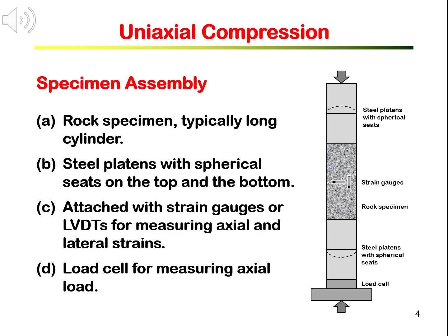We will need to measure deformation of the specimen during loading in order to calculate the Young's modulus and the Poisson's ratio. Therefore, there should be measuring sensors for axial and lateral displacements by either strain gauges or LVDTs. We will explain a bit more details on how to use strain gauges and LVDTs devices in the next slide. Measuring the axial loading is usually by load cell and it is normally built in the compression machine. If not, then a load cell should be attached to the specimen assembly for axial load measurements.